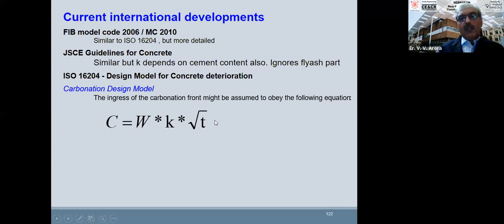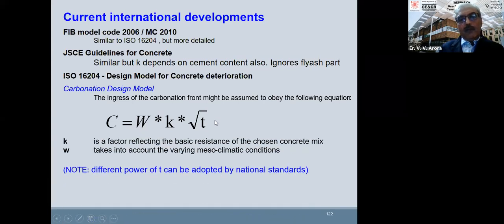We have done a lot of work on this model, but what we have seen, and some other researchers have also pointed out, is that this may not always be root T. The power can be a little different also. What we have seen is that when we use different kinds of cements, OPC, PPC, this may not be root. Then we have to use a different power, 0.4 to 0.6. I mean, T power 0.5 is the square root. But it can vary from 0.4 to 0.6. But the basic model is similar.